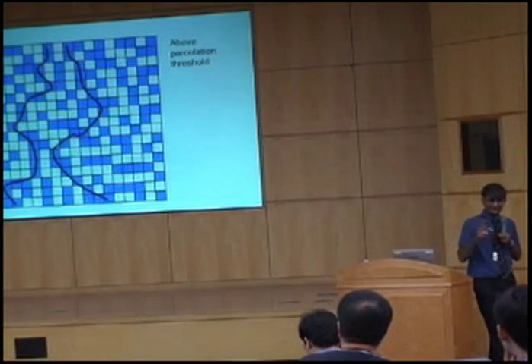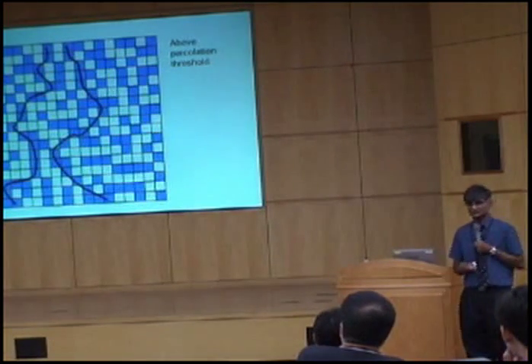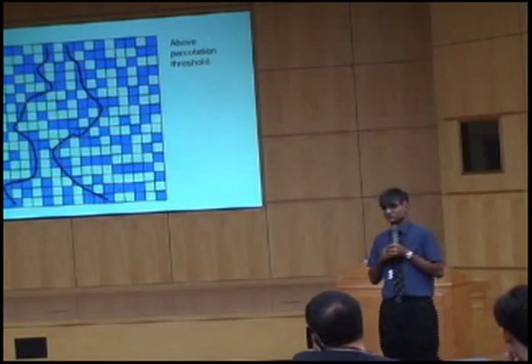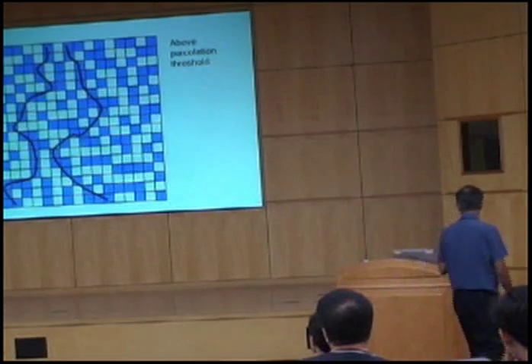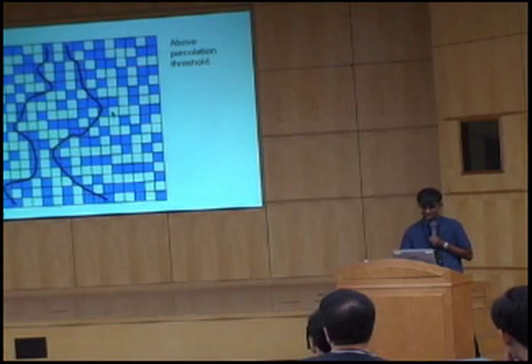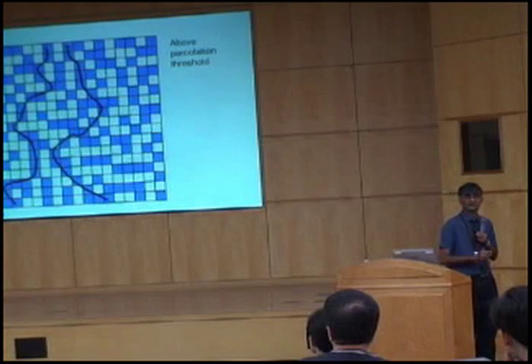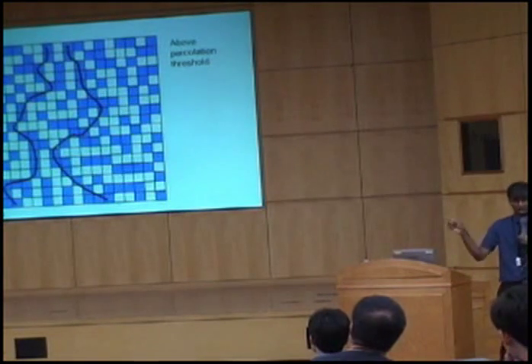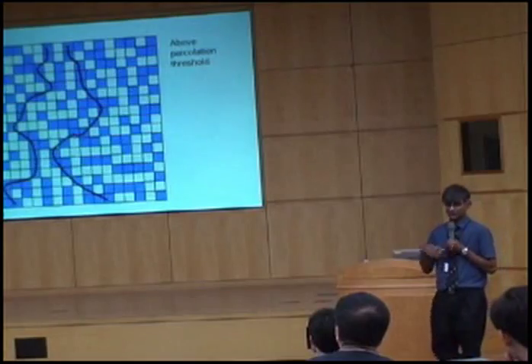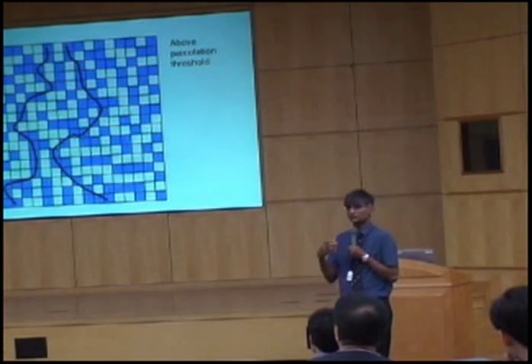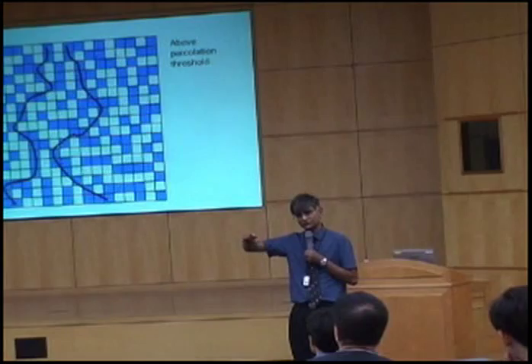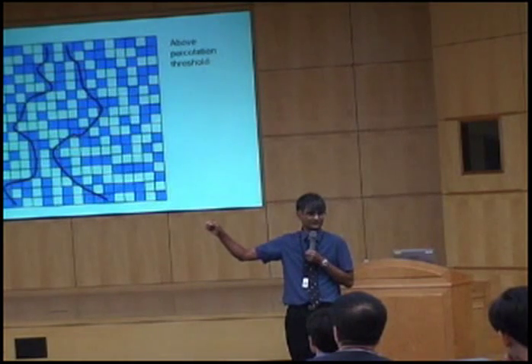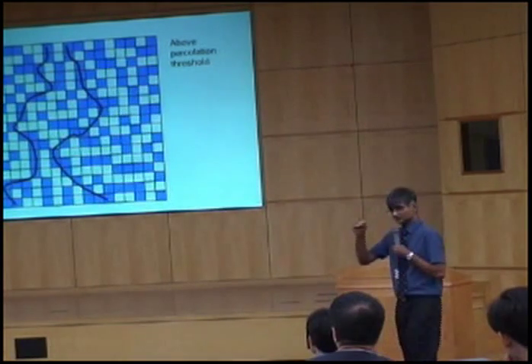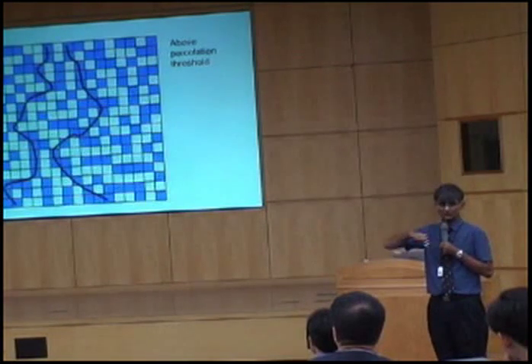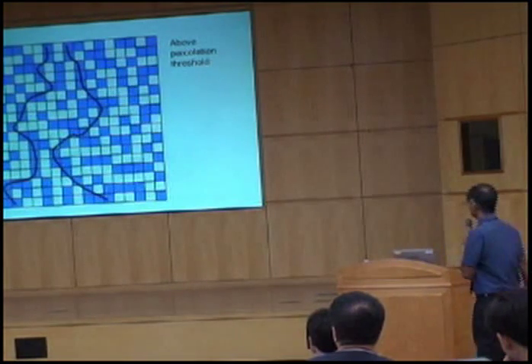Now, in this diagram, the blue part represents the austenite. And the volume fraction of austenite is such that I have a continuous path through the austenite here. So I can draw a line continuously from one end to the other end of this microstructure, only going through austenite. Okay? So we say that this microstructure has percolation. That means I can go all the way through the microstructure through just the austenite. Okay? So it's above a certain threshold which allows me to do that. So it's above the percolation threshold.